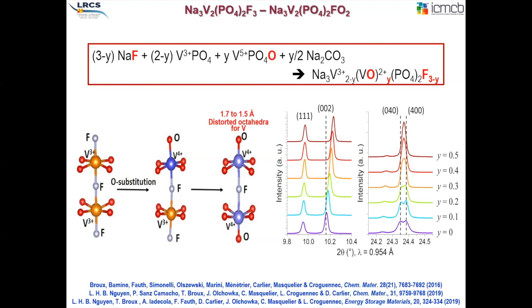We see clearly that depending on the amount of oxygen that has been substituted into fluorine, the structure changes and the lattice distortions of the orthorhombic cell change, and thanks to precise crystallography and precise X-ray diffraction, we can monitor and measure the amount of oxygen we have been able to substitute for fluorine.